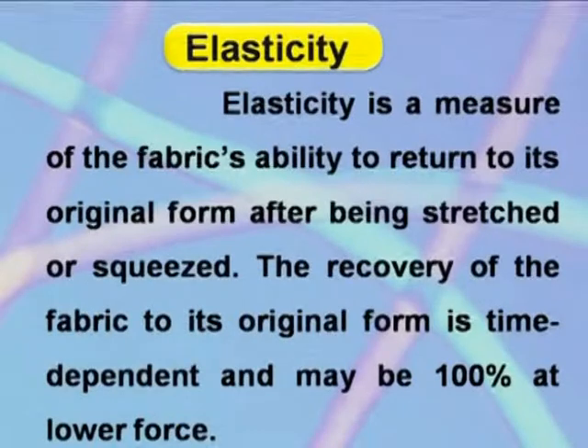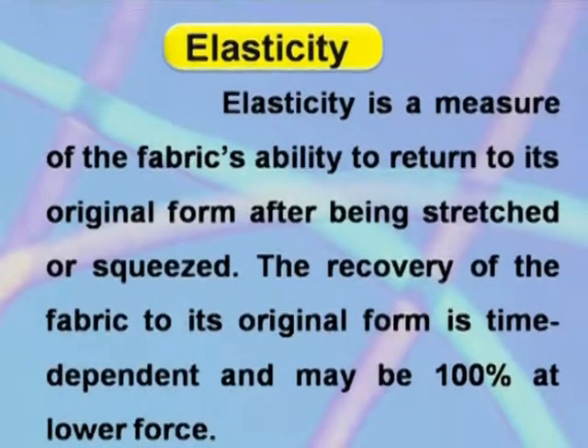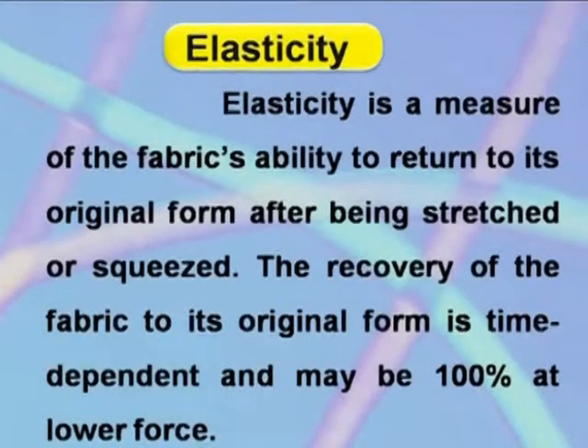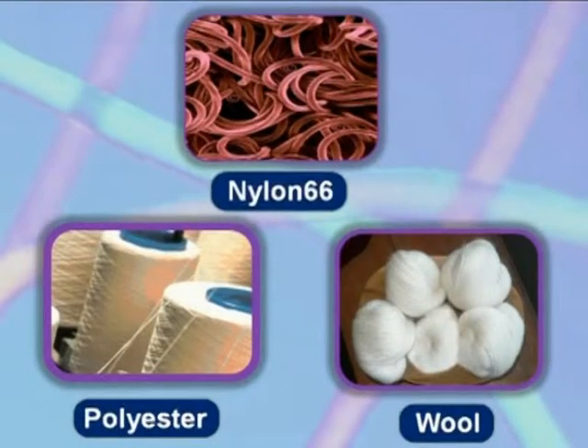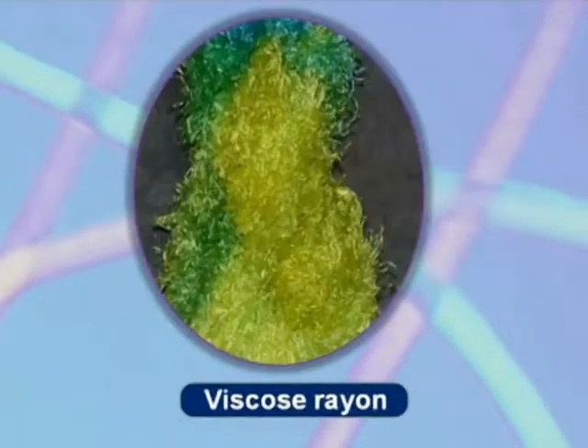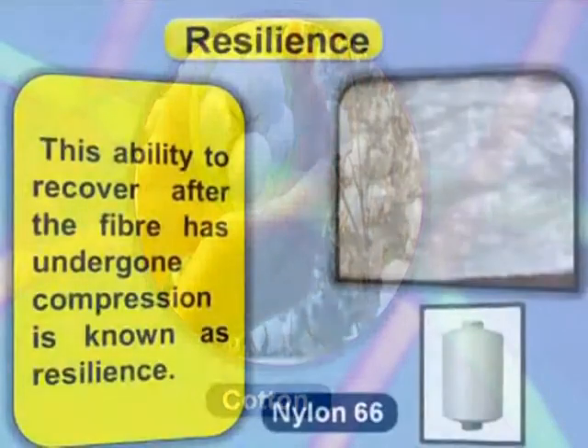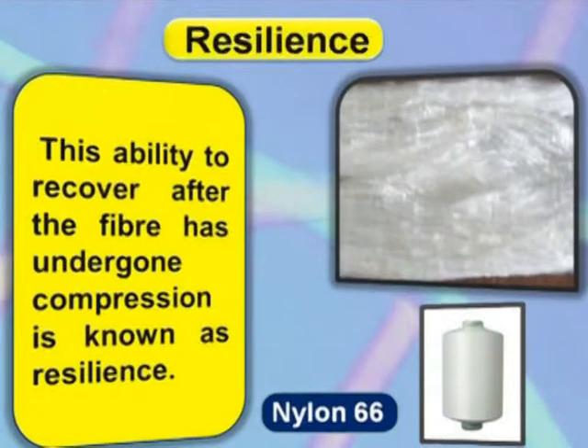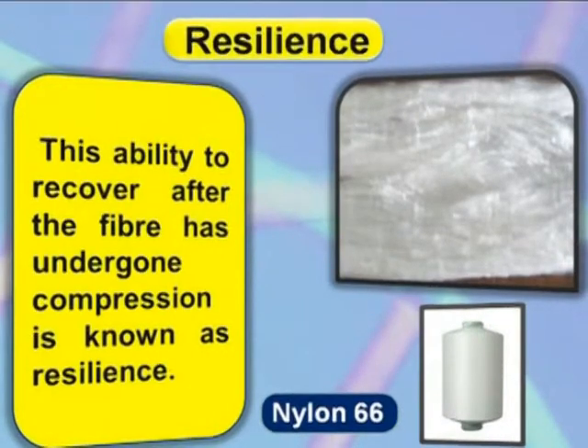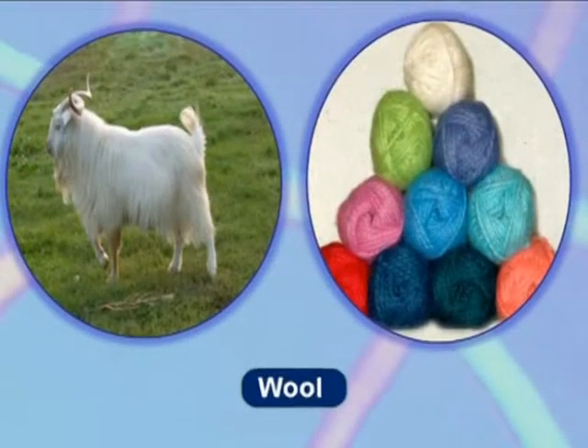Elasticity is a measure of the fabric's ability to return to its original form after being stretched or squeezed. The recovery of the fabric to its original form is time-dependent and may be 100% at lower force. Nylon-66, wool, and polyester fibers show good elastic recovery even while undergoing quite large extensions. Silk, viscous rayon, and cotton show poor recovery. This ability to recover after the fiber has undergone compression is known as resilience. Nylon-66 and wool possess high resilience.